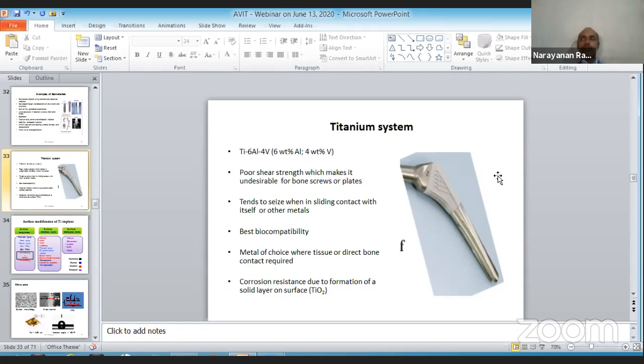So although you should use metallic implants for certain good values, there are also adverse effects like leaching out and being carcinogenic, causing diseases like Alzheimer's disease or toxicity. That is the reason why we can go for coating. If you go for a surface modification or coating, you may to a certain extent prevent the leaching of these carcinogenic elements. So, they are good. Probably I may give 80-90% marks, but 10-20% I have to go down.